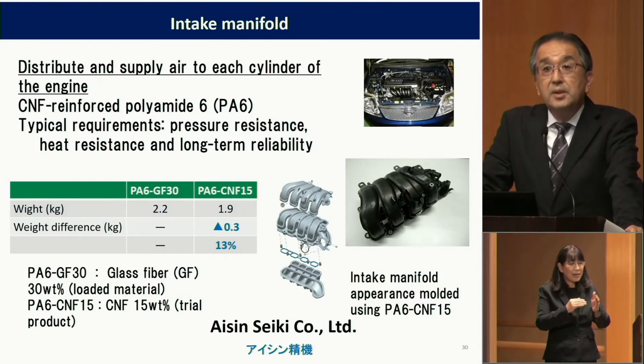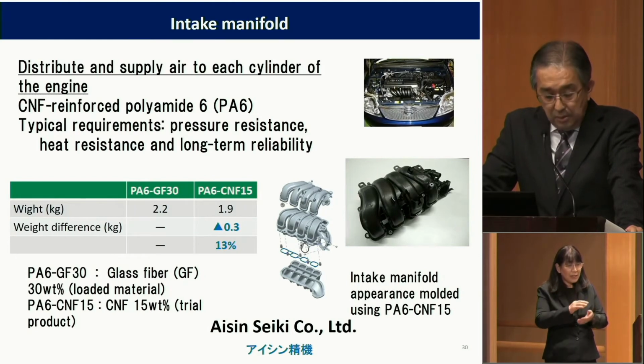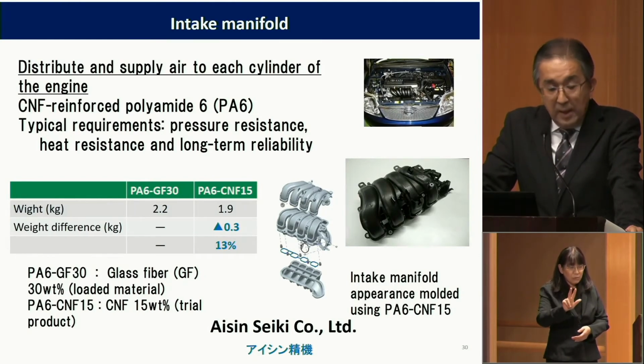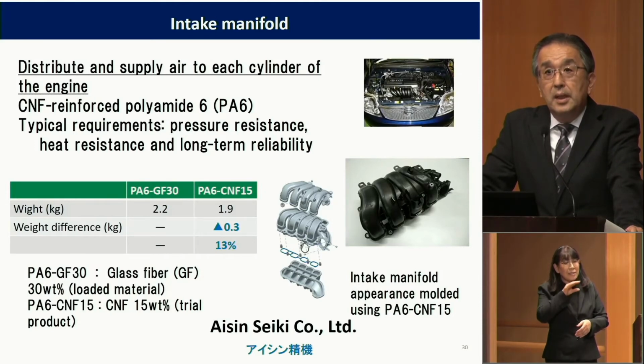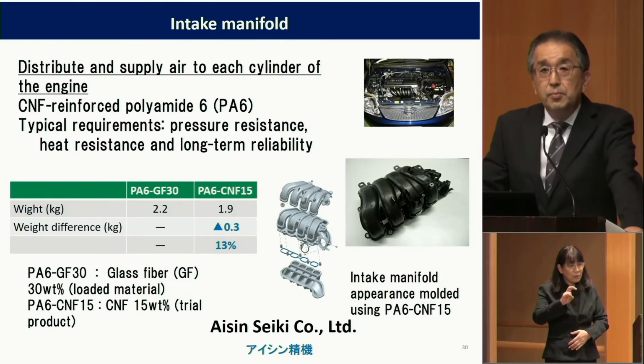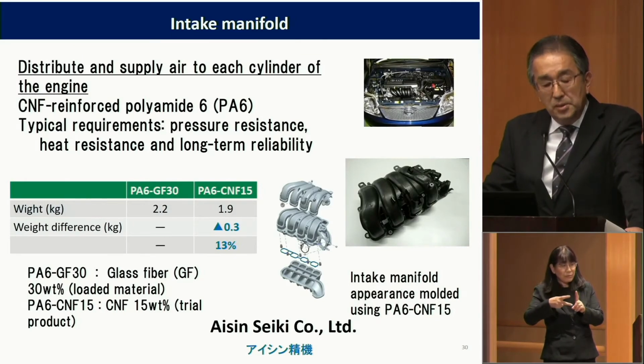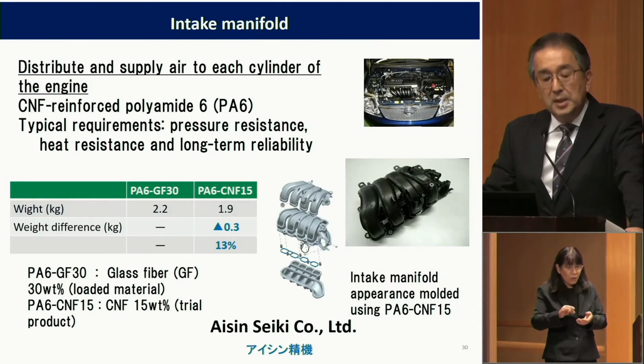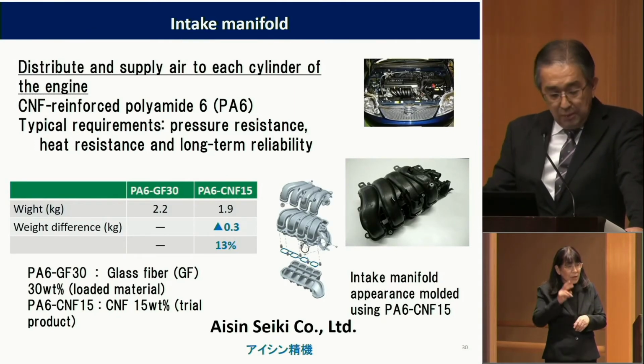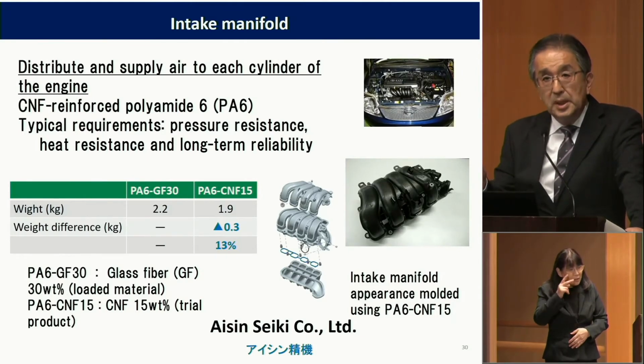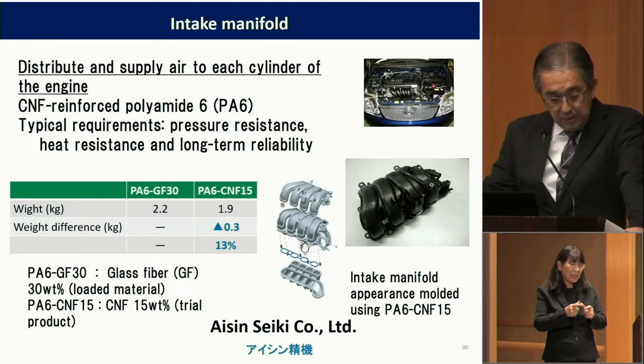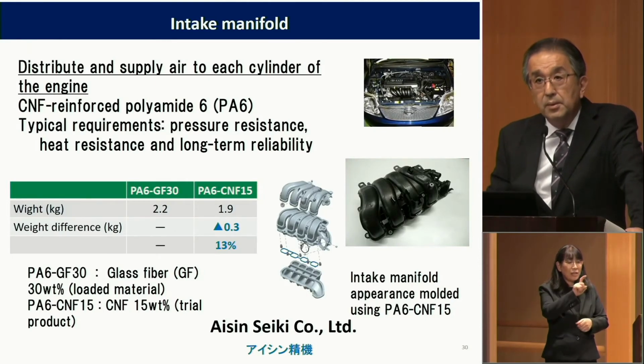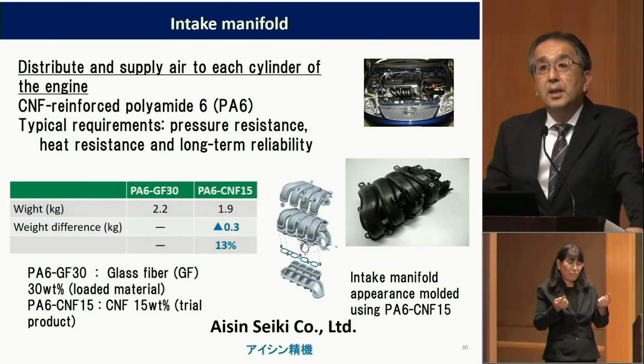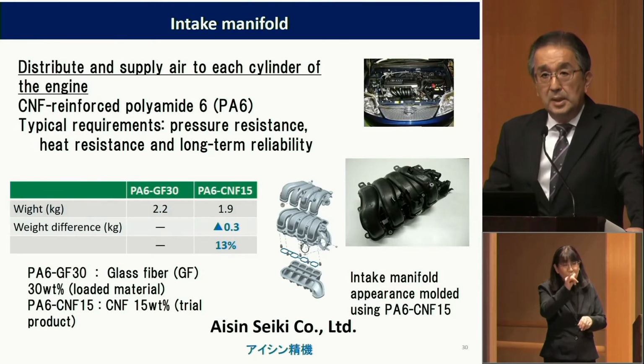This is a prototype intake manifold made of polyamide 6 CNF composite. The current product contained glass fiber of 30%. But adding 15% CNF to PA6 increases the modulus about 2 times. So it's almost the same as glass fiber. So the specific gravity is smaller than the glass fiber, and the total weight was reduced about 13%. This was made by Aisin.